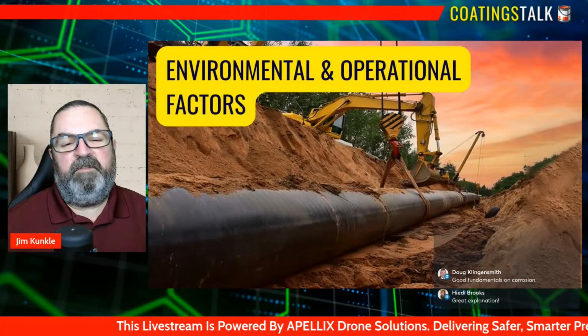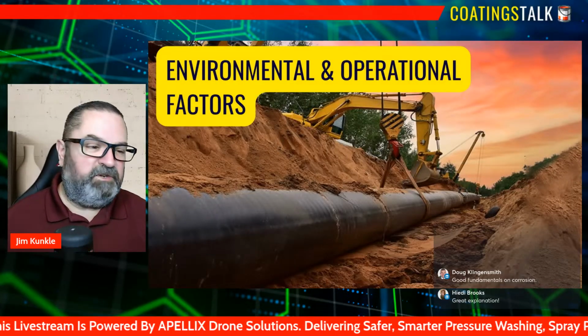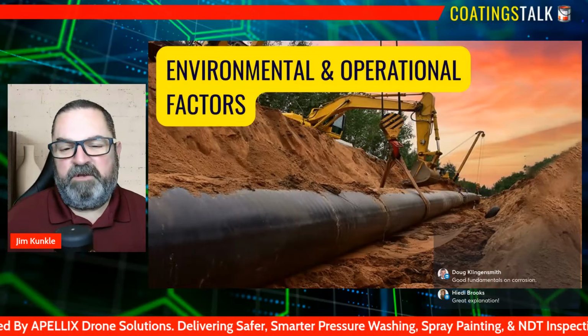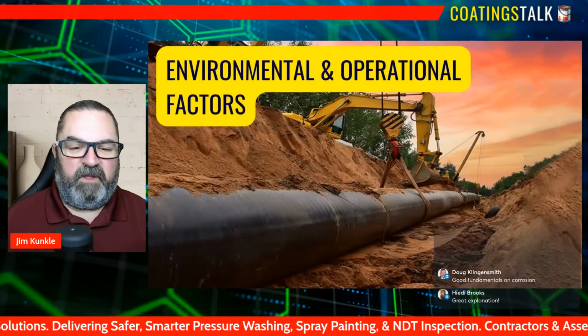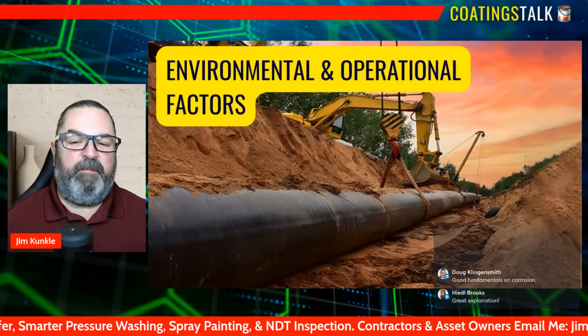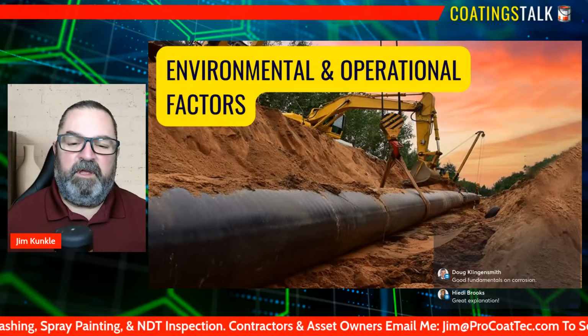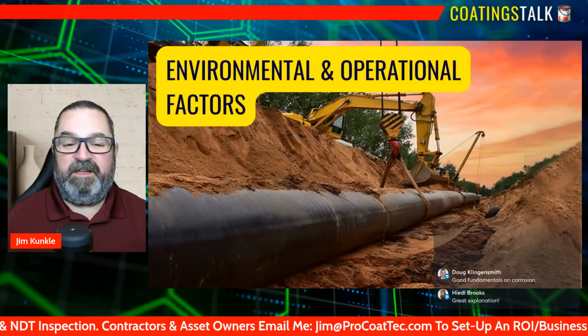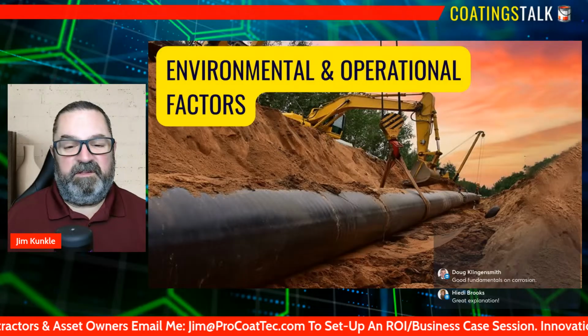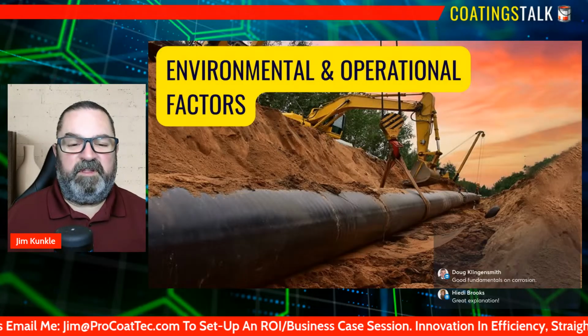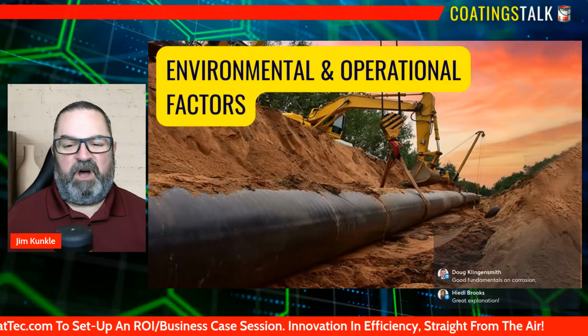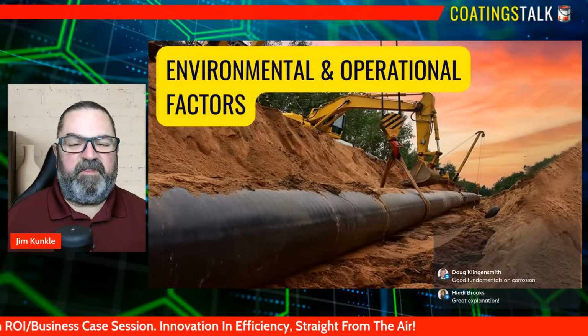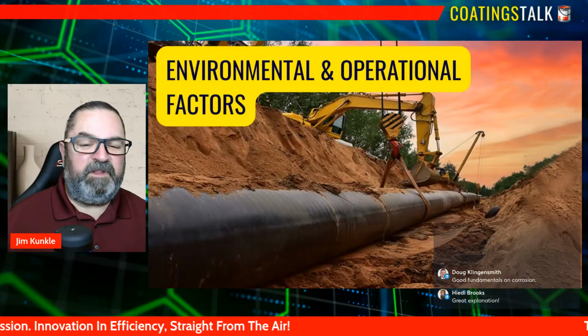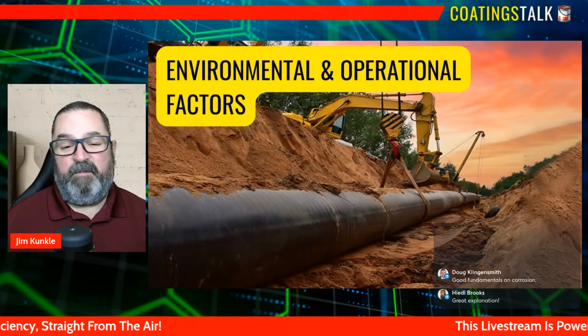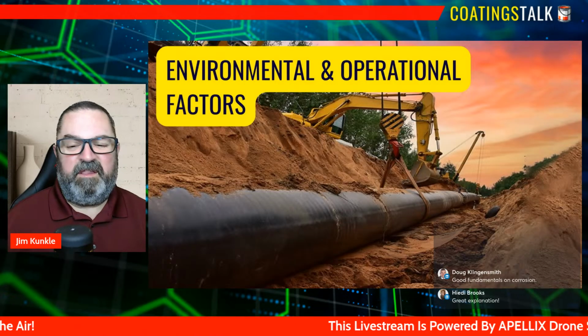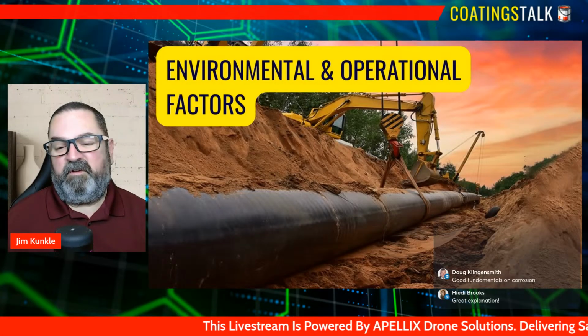So, the role of design flaws in poor coating application. Design flaws play a major role in how quickly corrosion develops, often creating conditions that even the best coating system can't fully overcome. When assets are built with sharp edges, tight crevices, complex geometries, or hard to reach surfaces, these areas naturally become corrosion hotspots. Edges tend to receive thinner coating films, crevices trap moisture, water, and contaminants, and intricate designs make it difficult for applicators to achieve proper surface preparation.